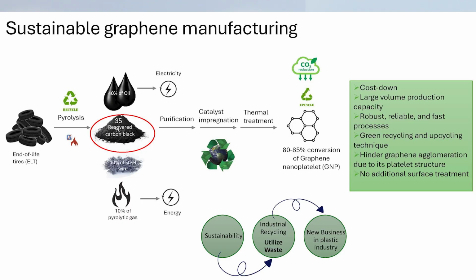First of all, we are starting with end-of-life tires and getting carbon black. It's about 35% recovered carbon black. Here we need to profile the carbon black efficiency for the conversion to graphene-like structures. This is not a graphene sheet in the end. This is a platelet form in bulk form, and it can be used as an additive. Instead of using a compatibilizing agent in the compounds or additives, you can use it as a multifunctional additive in one formulation. And this brings an advantage especially in cost.